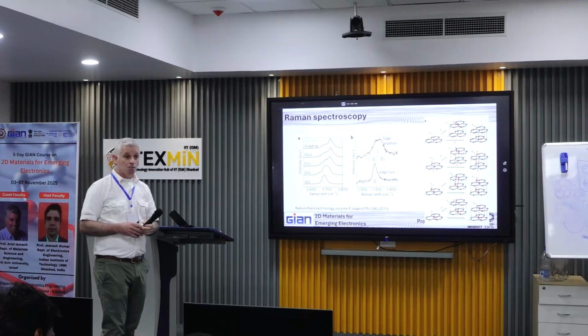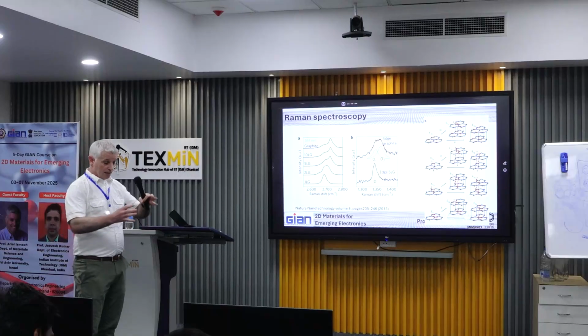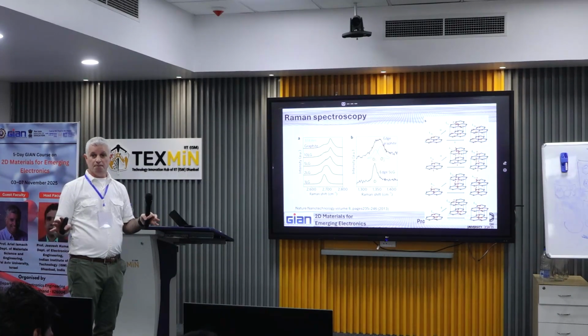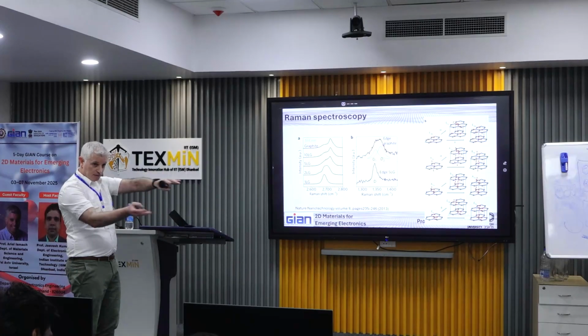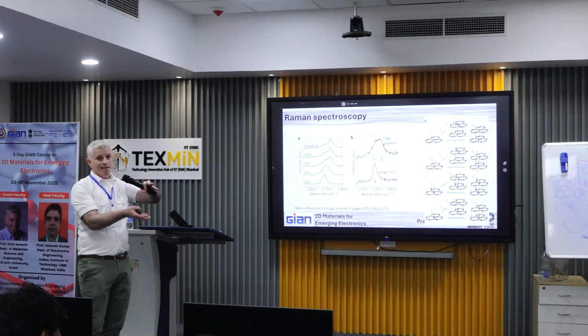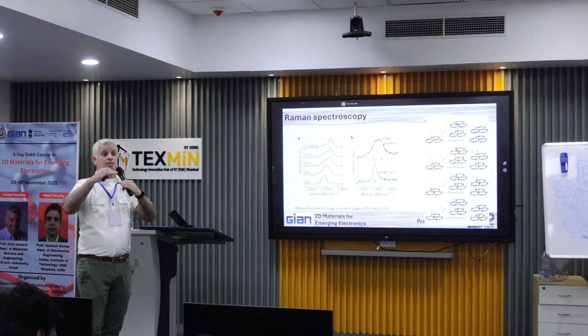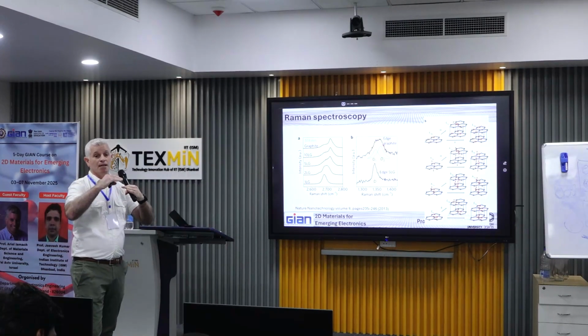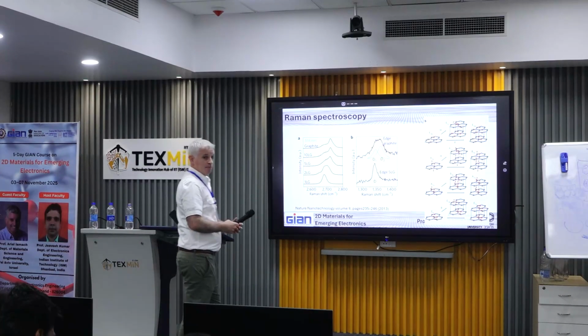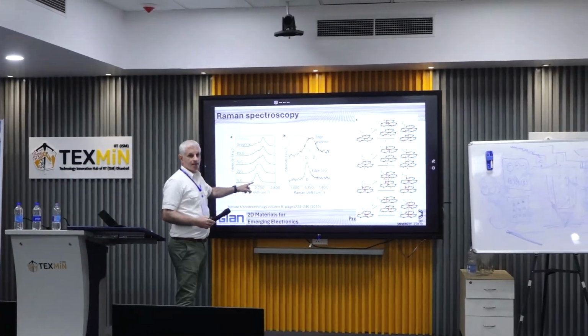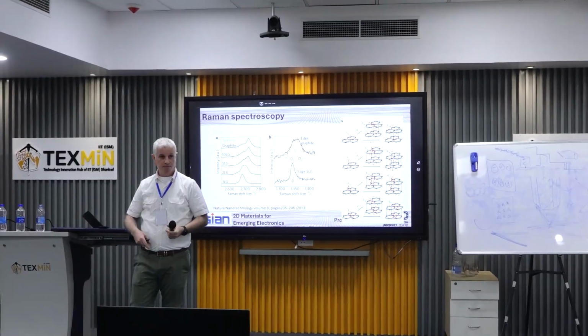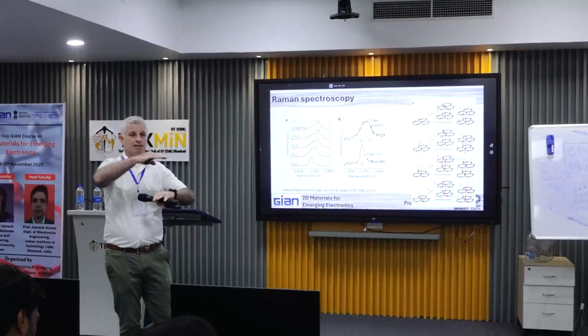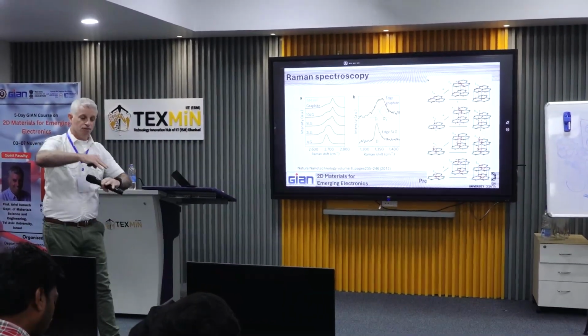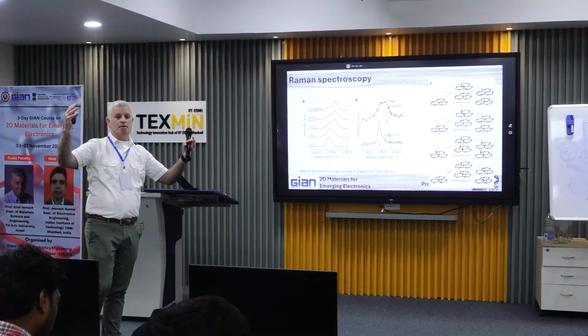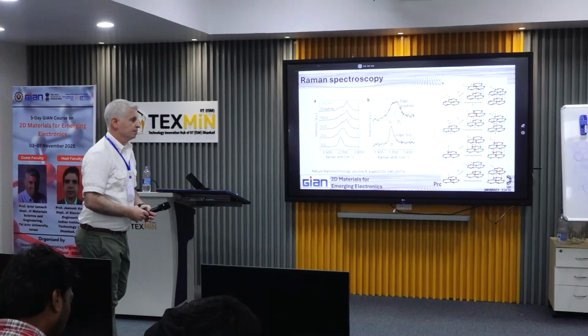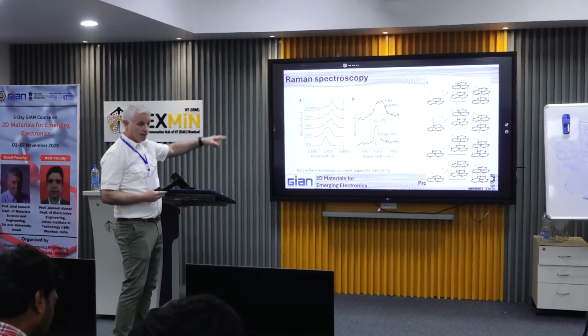Because if you have a multi-layer profile or even a graphite that is completely turbostratic, you remember turbostratic, that all these layers are rotated. When you rotate the layers, you basically increase the distance just a bit between the layers. And this sometimes causes it to look like a single layer. So you get a single peak. It's like you isolate the layers, basically. Even if you have a graphite, you isolate the layers. So you have multiple single layers. But in any stacking, you should get the above.